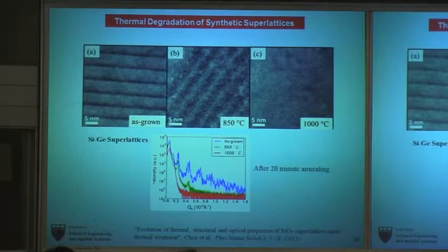And you can see that in terms of the X-ray scattering. As grown, you see these periodic oscillations, which are telling you have this periodic structure, the nanostructuring. And with time, you see this intensity scattering regime becomes flat, smoother and smoother. So these oscillations are dying away.